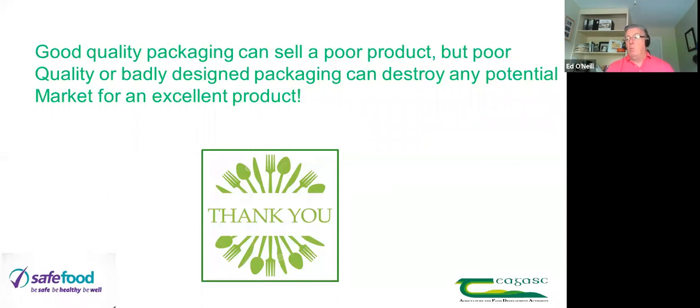But one of the problems that people fail to see in terms of biodegradable is the actual sealing medium is usually something like ethylene vinyl alcohol, EVOH, and that is non-compostable. But it makes the seal very proper. So a lot of work needs to be done on getting the sealing medium right. It could be polyethylene, but polyethylene, while it's recyclable, it's not compostable. So there are technical challenges out there, and there's a huge amount of work being done behind the scenes, especially in Germany, on that. And it's something we just have to progress with and embrace.